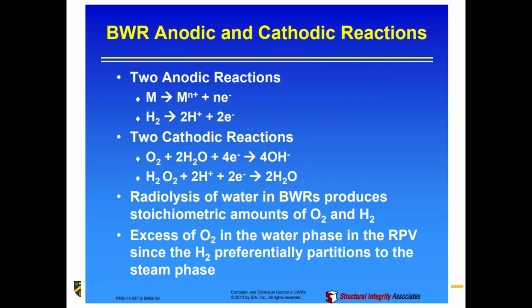So two anodic reactions. Let's go over why this strategy works, just to recap things. Our two major anodic reactions that can happen in this case is our metal can dissolve, or we can do something with hydrogen. So this might seem kind of obvious, but if you pump a whole bunch of hydrogen into the water, guess what? Just chemical wise, you're going to have more of that reacting than your metal. You're going to save your metal, basically. Pretty simple. The two cathodic reactions in this case are going to be oxygen, residual oxygen present as well as created through radiolysis, as well as hydrogen peroxide. Our old friend hydrogen peroxide is back because, again, radiolysis products. So the basic way this works is the combination of hydrogen with these two. We'll talk about that in a bit.